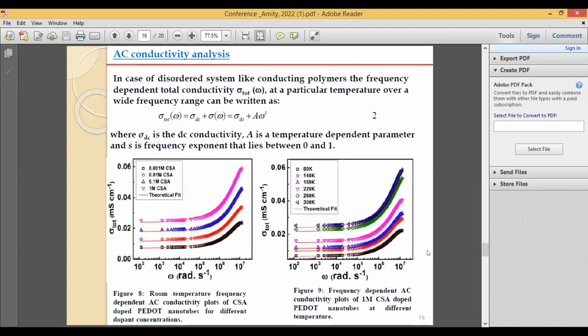Then we have performed AC conductivity analysis. The AC conductivity analysis was done at room temperature for all the samples, and at different temperatures for the highest doped sample. From there we have seen that in the lower frequency region, it almost shows frequency independent characteristics, which we can say is the contribution of the DC part, and the dispersive behavior in the high frequency region corresponds to AC. In order to understand the transport mechanism in our system, we have fitted our highest